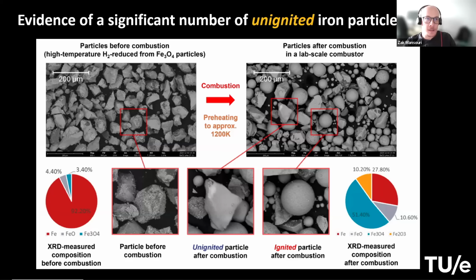So the second question is, since most of the particles we got are porous, and even after combustion and after inspecting the cross sections of the burnt particles, we still find pores inside the particle. Do the pores go away after different cycles of reduction?